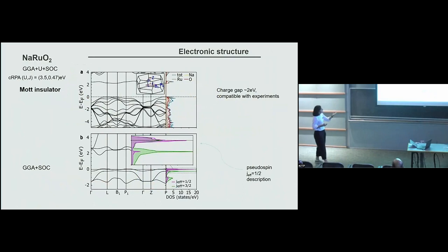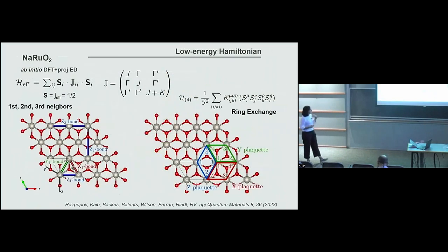When we look at the electronic structure of this material, one can find that this is a Mott insulator, with a well-defined pseudo-spin J effective 1/2, like in the honeycomb alpha ruthenium trichloride that I was showing to you. And when we now extract the exchange interactions by this multi-step process, what is important in the triangular lattice is not only the bilinear contributions, but also the fact that you may have important ring exchange. I'm going to talk in a moment about the ring exchange.